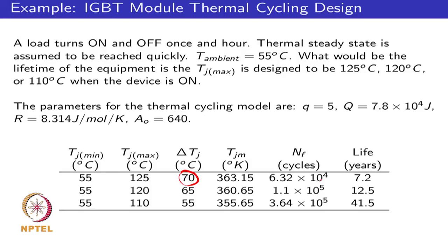and you can get an expression for the life of the equipment, because we know there is one cycle an hour. So you take this divided by the number of hours, number of days a year, and you get 7.2 years. So you can expect a life of the order of 7.2 years if you are designing with a junction temperature of 125. If you reduce your maximum junction temperature to 120, then your delta T reduces, your TJ mean reduces by some extent, your number of cycles to failure now increases, and you get about 12.5 years.